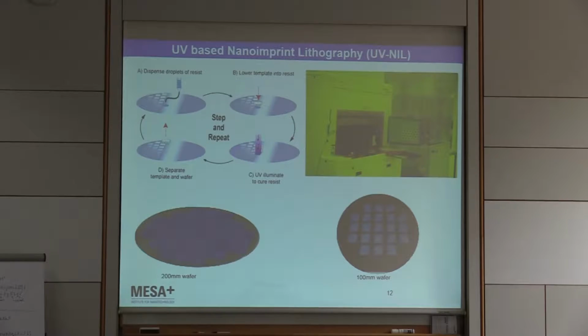So from there on, you would do your regular lithography steps as you would do them for e-beam or optical lithography. So this is the machine that we have in Twente. It's a machine from Molecular Imprints, Imprio 55. And the nice thing about it is that it's a so-called step and flash machine. So on a wafer, you can make multiple imprints as shown here. The alignment is not as good as you can get with a wafer stepper, but at least you can make a number of copies on a wafer.